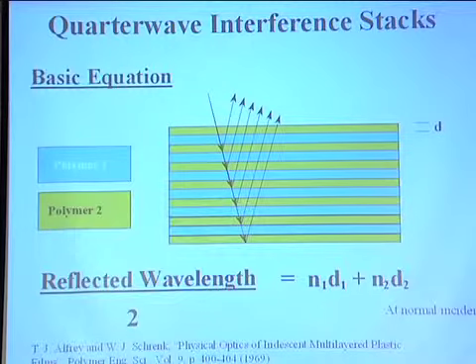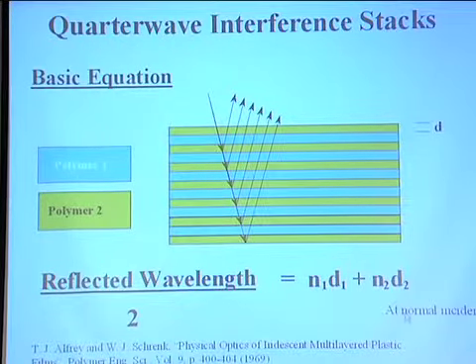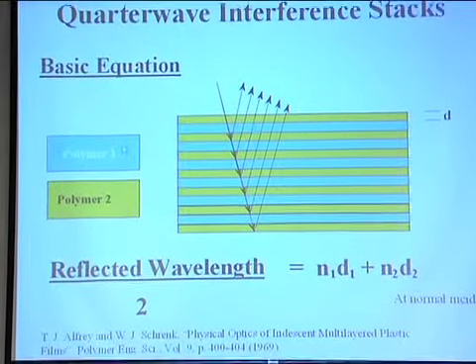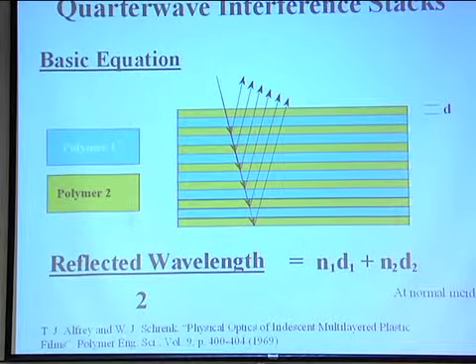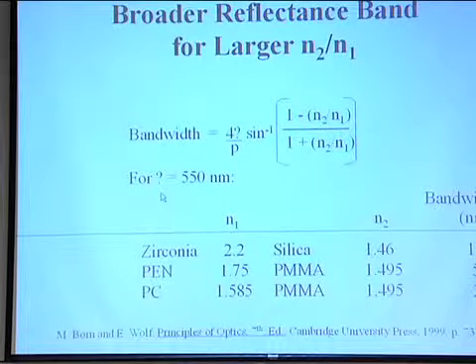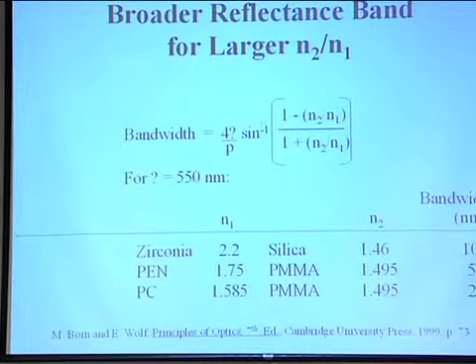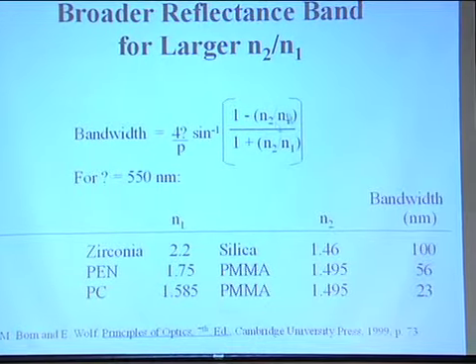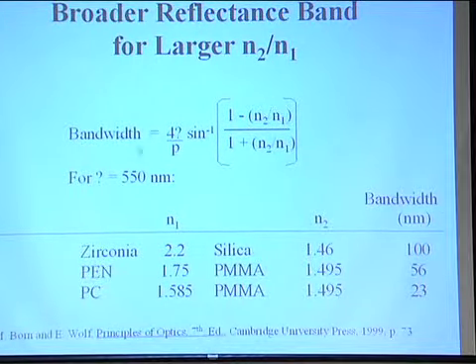The basic equation, again, is you have 2 different polymers, and the reflected wavelength of light is 1/2 the thickness of the 2-layer pairs added together. One polymer has a high refractive index, the other polymer has a low refractive index. And depending on which polymers you choose and their refractive indices, you can make the bandwidth, the reflection band, very wide or very narrow with high reflection.